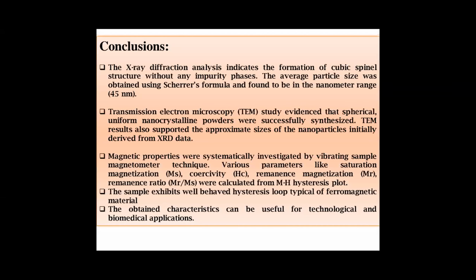And then conclusion. The X-ray diffraction analysis indicates the formation of cubic spinel structure without any impurity phase. The average particle size was obtained by Scherrer's formula and found to be in the nanometer range, 45 nanometer. Okay. Then transmission electron microscopy study evidences that spherical uniform nanocrystalline powder were successfully synthesized. Then results also supports the approximate size of the nanoparticle initially derived from XRD data.